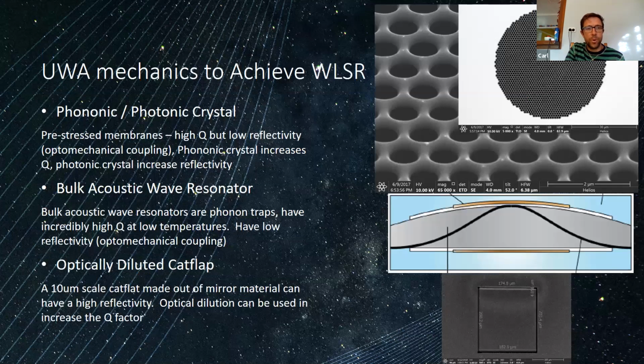So we were investigating 3 different mechanical resonators. Phononic crystals are a pre-stressed membrane. They inherently have a very high Q factor, and a phononic crystal lattice is punched as holes into the membrane, and the phononic crystal forms a band gap. Then you have some defect in the middle of the lattice, and the phonons in the defect mode, the resonant mode, are trapped in the defect and can't escape to the outside. I'll go over some results very briefly because I'm sure I'm going to run out of time.